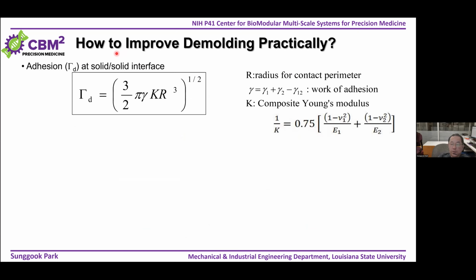So after the polymer is completely filled into the mold cavities, now we have to consider the next step, which is the separation of the molded substrate from the mold, and which is called demolding. Okay, so the question is how we can improve demolding. Okay, so this is actually one of the simplest models to describe the adhesion at a solid interface. Okay, so you can see the adhesion is a function of surface tension. Okay, this is the work of adhesion, and K is basically the composite Young's modulus, and R corresponds to basically the contact area. Okay, so basically by controlling those factors, we want to reduce the adhesion between the molded polymer and the mold surface.